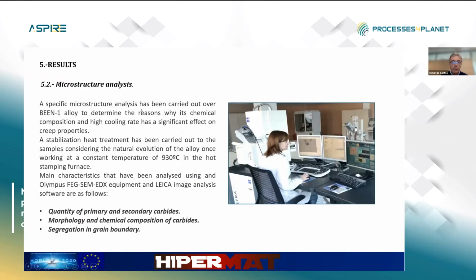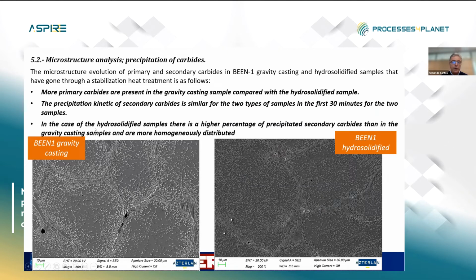We have tried to investigate and analyze the reason for this behavior. So we have gone over the analysis by means of SEM and EDX of the quantity of primary and secondary carbides, the morphology and chemical composition of carbides, and the segregations in grain boundaries. What have we seen? Well, first of all,